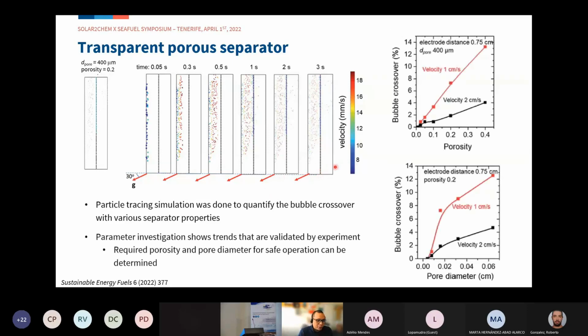Parameter investigations were done as shown over here as a function of porosity and pore diameters, which we validated with experiment. The important thing from this is that the analysis will be able to tell us what are the required porosity and pore diameters for safe operation.